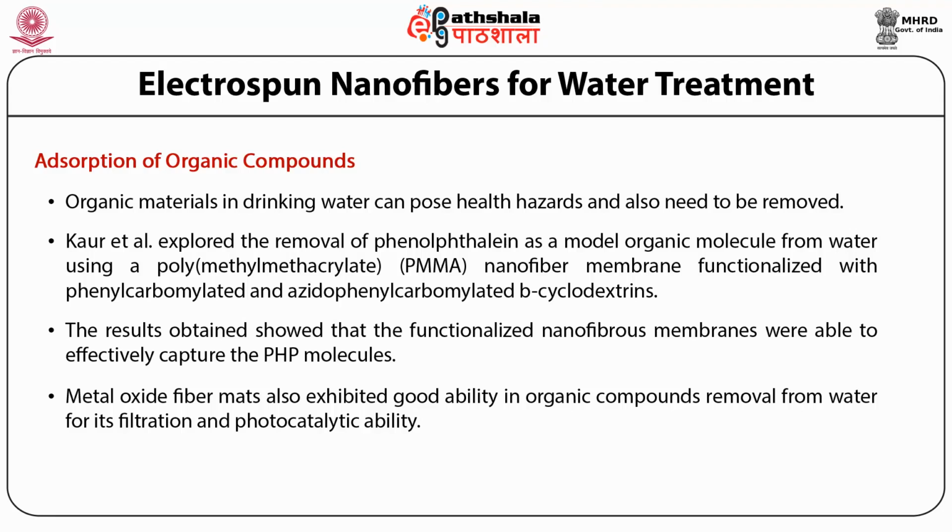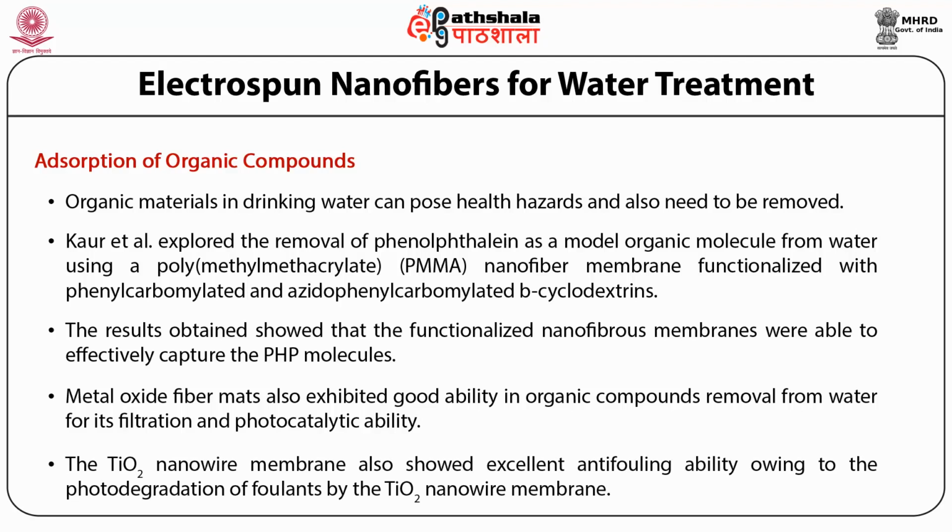In this study, TiO2 nanowire membrane achieved nearly 93% removal rate of humic acid with total organic carbon, respectively, via a co-current filtration and photocatalytic oxidation. The titanium nanowire membrane also showed an excellent anti-fouling ability owing to photodegradation of pollutants by the TiO2 nanowire membrane.